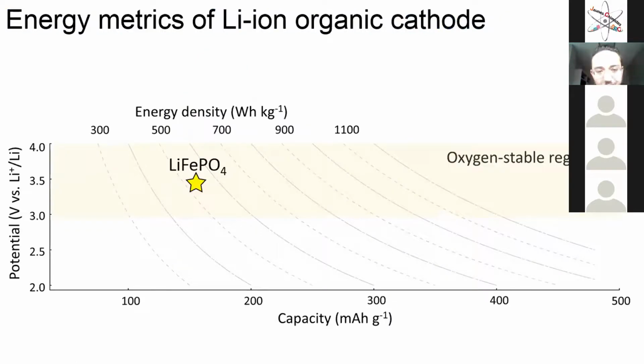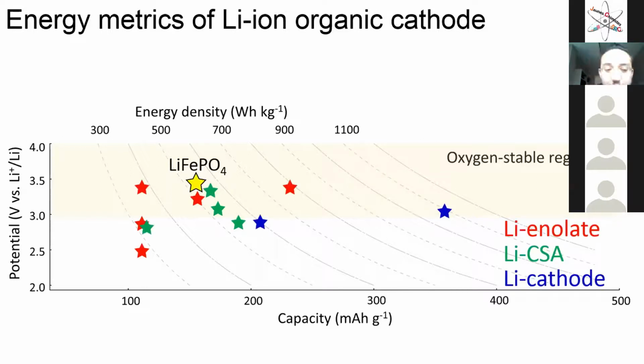So in order to compare this, our target for lithium containing organic cathodes is LFP, lithium iron phosphate. We want to make something that can behave exactly as lithium iron phosphate, can provide the same energy density, the same power density, and we can process it as lithium iron phosphate. So now we do have pretty much molecules. In 2015, we had only one that is very low as compared to lithium iron phosphate. Today in 2021, we do have many chemistries. Some of them are lower, some of them are comparable, but others can be even better than lithium iron phosphate. We just need to work hard on them in order to improve even more their electrochemical performances and processability.